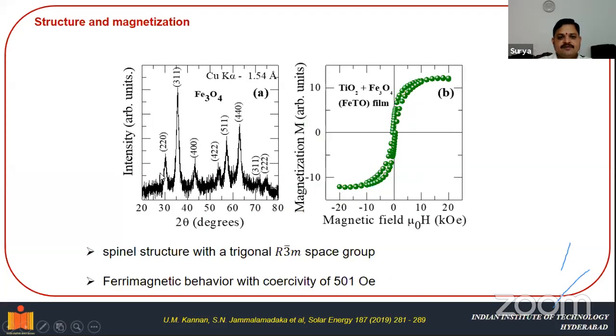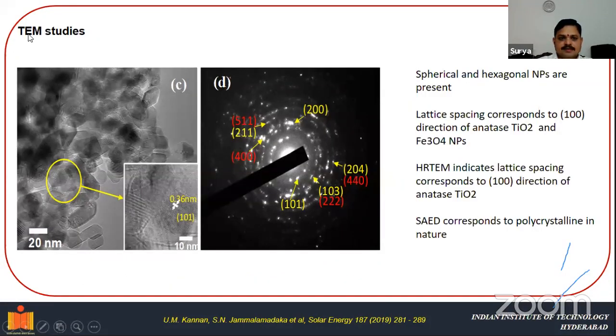So this is the kind of structure that we have obtained for Fe3O4. The spinel structure with a tetragonal or Fd-3m space group, and we could see a ferrimagnetic behavior. The ferrimagnetic behavior for the titanium dioxide plus Fe3O4 device. Okay, as you can see, this is a kind of ferrimagnetic behavior, and it is having the coercivity of the order of 501 oersteds. So these are the TEM studies, the transmission electron microscope studies.